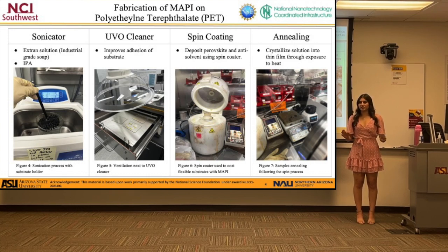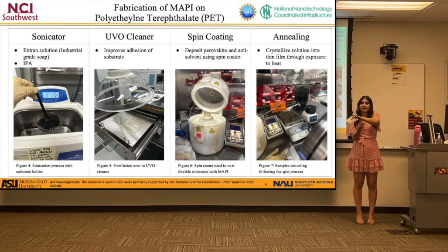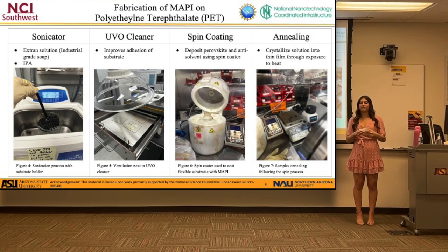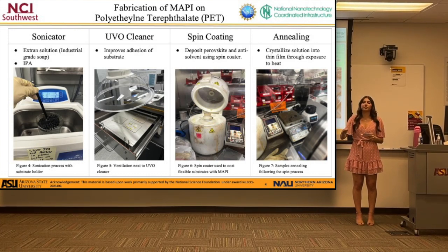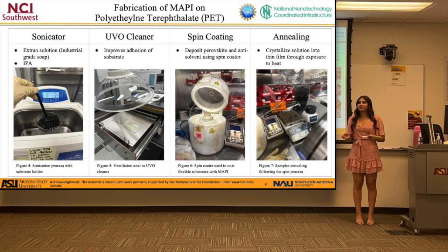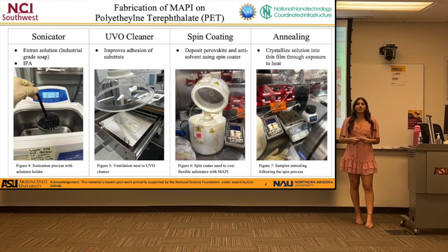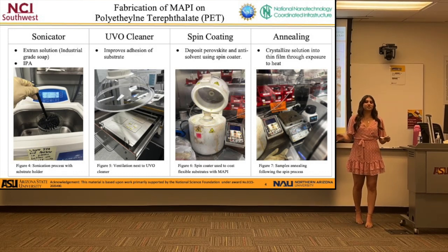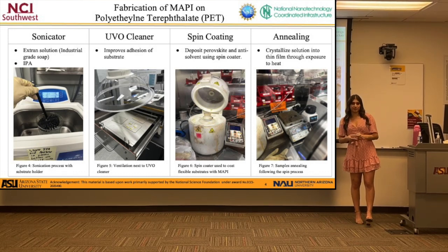And the manner in which this spin coater works is that there's a substrate that we have and there's a vacuum, so that when the substrate is spinning, it doesn't fall off. And so the reason why this works is because it uses centrifugal force to create a uniform thin film. So when the perovskite is deposited, it can evenly create a uniform surface. And then finally, the last part in this step is annealing, which allows the device to fully crystallize due to extended exposure to heat.